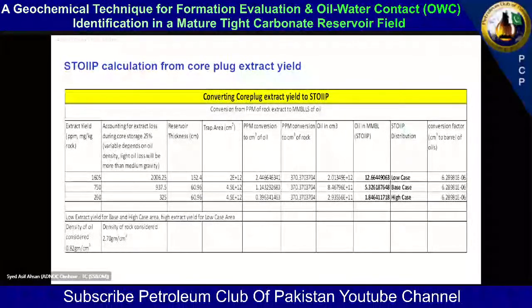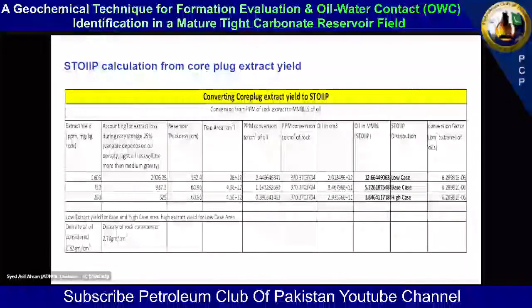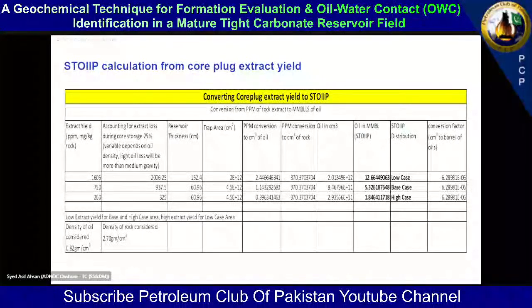However, in this case, and this has been done for all the unconventional resource assessment, the source rock or tight rock based resource assessment is done as follows. You take a rock sample, of known weight, and you measure the extract yield. Since you know what rock it is and what density it has, you can calculate the volume of that rock which you have utilized to extract it. So knowing the volume of the rock and the volume of the oil, you can calculate the STOIP for the entire extent of your field using the extract yield data. Okay, and this is what I have done here.